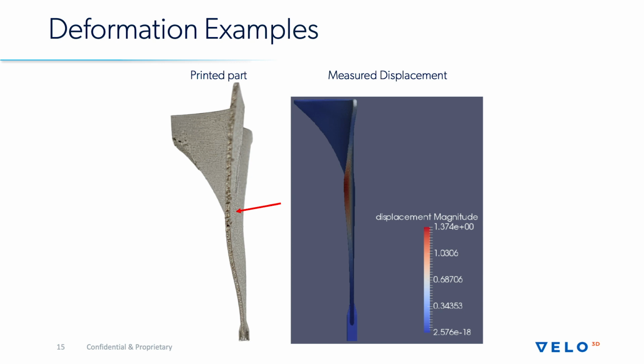Well, what happens when we actually print that part, which you can see on the left-hand side here, and then we use a 3D scanner to measure the displacement of the geometry to what was intended in the CAD file, you can see that those edge fins are actually deviating from their expected position by over 1.3 millimeters in this case. So you can get very large macroscopic deformations in these types of objects as you're printing it, just due to the residual stress that's building up while you're printing the part.